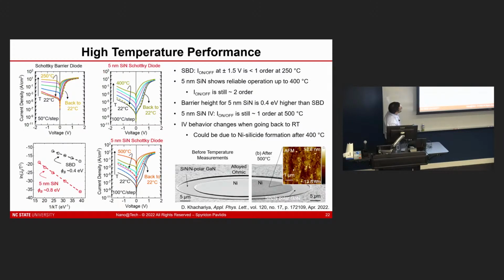And so I'll just briefly show this here. This was a control device that already at 250 degrees was basically resistive. I mean, there's no rectification effectively in this device. But with a 5 nanometer silicon nitride layer, we can still see a rectifying diode at 400 degrees Celsius. And so that takes advantage of the larger barrier height that we're engineering through the inclusion of the silicon nitride layer. And we even showed that if you go to 500 degrees Celsius, your device still survives.